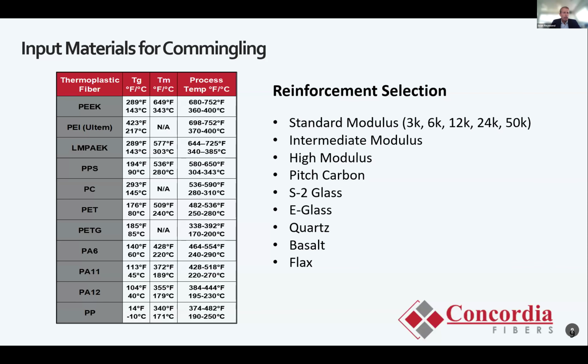And just so everyone has a sense of what material inputs are possible in commingling for thermoplastics, it's pretty much any polymer that can be made into monofilament or multi-filament yarn can be used in our commingling process. So this table on the left is organized from mostly hotter temperatures to lower temperatures, but the temperatures also closely guide us down the level of mechanical properties and temperature resistance.